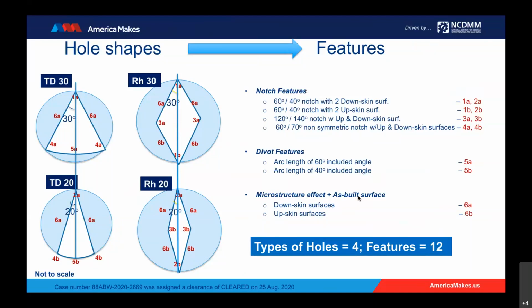A notch in itself has an included angle, and the surfaces inside the notch can be a downskin surface, meaning it's looking down, the underside of an overhang, or an upskin surface, which could be the face that is looking up. So we've come up with a nomenclature and variable structure to quantify these hole shapes into basis features. In extension, these 4 holes shown here end up being 12 different features.